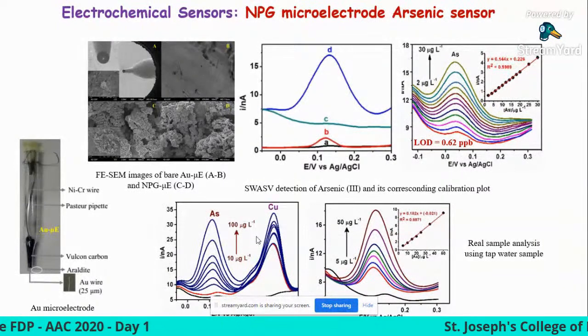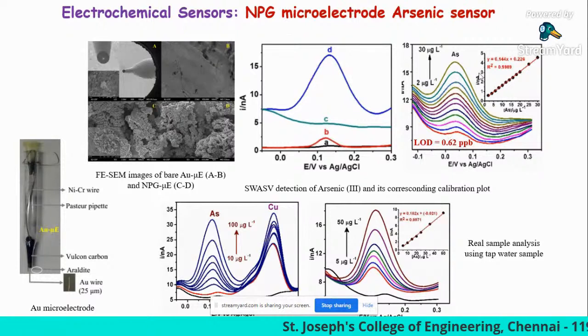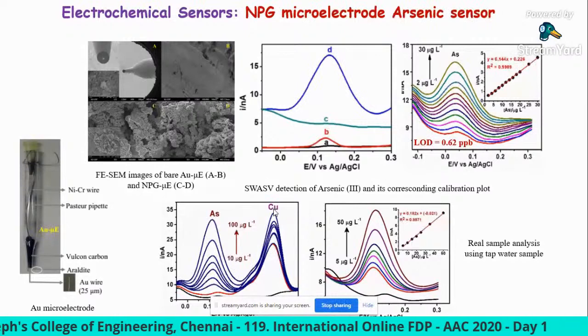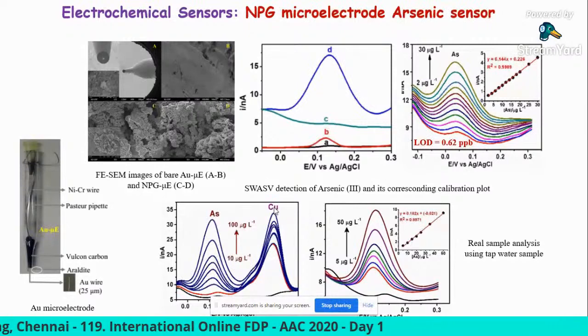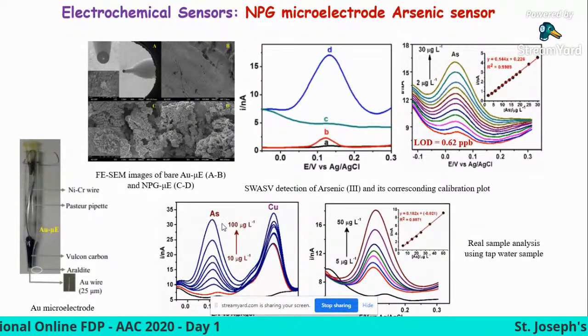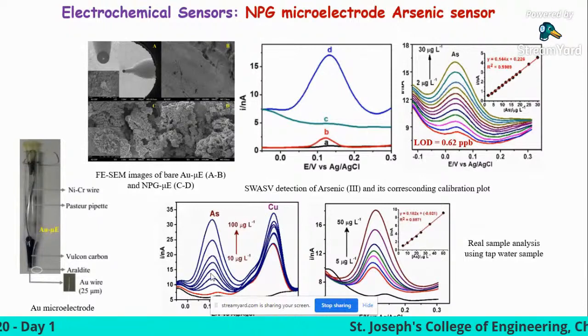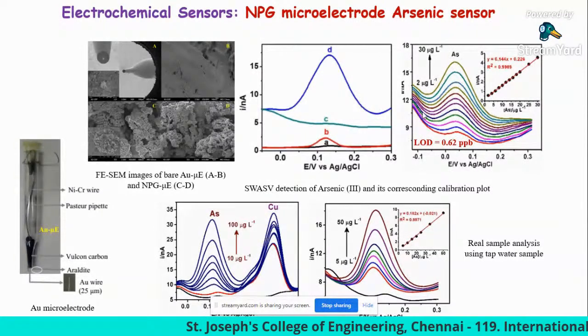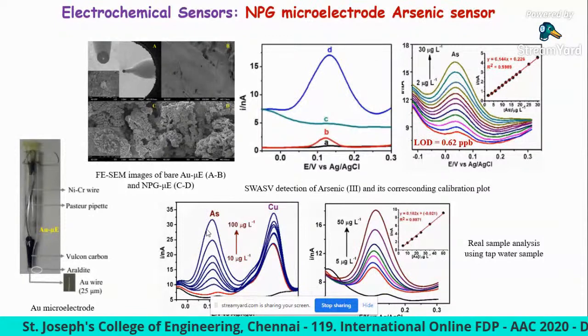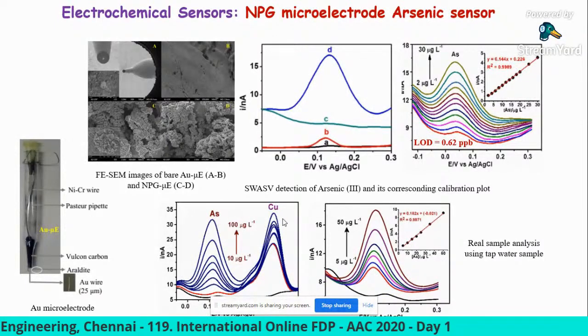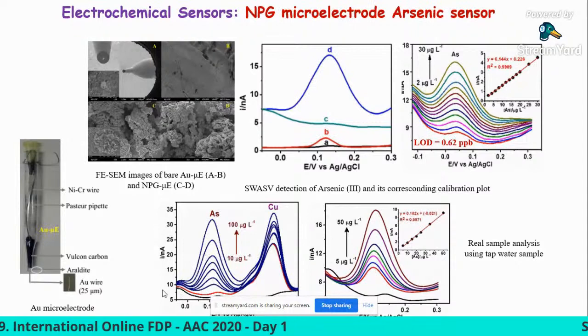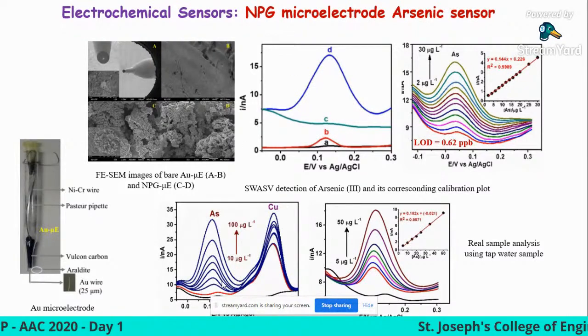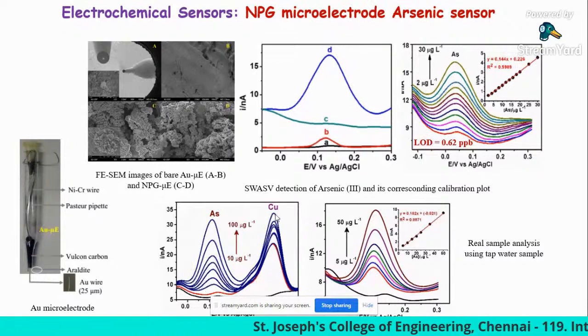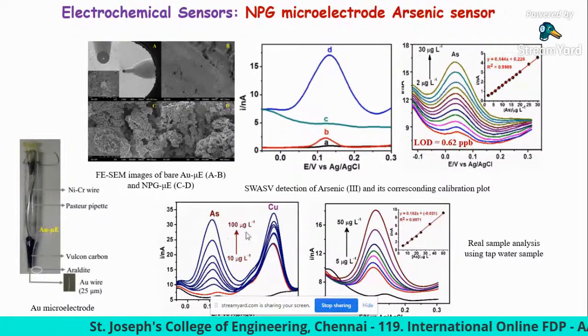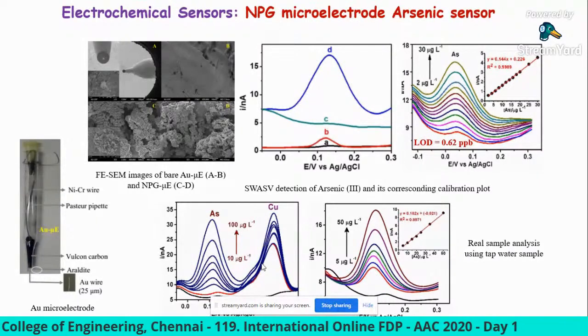In order to evaluate the interference when you detect arsenic, copper is one of the major interferences, because normally the copper stripping peak also appears at the same potential. So that is one of the major problems. Without modification, even if you have arsenic and copper, you will get a single peak. However, in the presence of the nanoporous gold microelectrode, there is a clear separation of copper and arsenic. It's almost around 300 millivolts difference, which is more than enough for